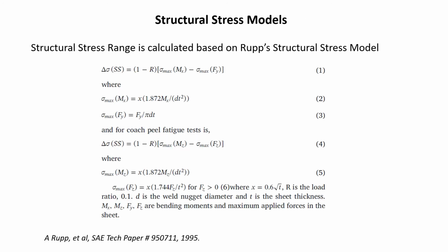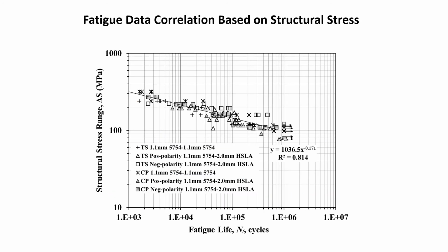And then structural stress range is calculated based on Rupp's structural stress model. This model only considers weld nugget diameter and sheet thickness. Using this model, we got this result, and it reveals that all fatigue life data points from both the tensile shear and coach peel configurations fall onto a single master curve with fitting coefficients around 0.8. This indicates that the weld nugget diameter is the controlling parameter for the fatigue life.